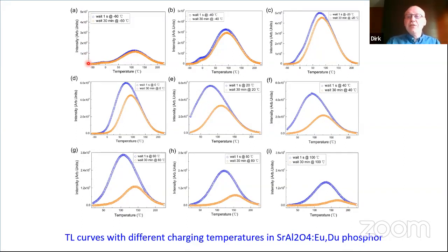It's too cold, and there's not enough thermal energy to liberate these charges from the persistent phosphor. So this also means that we cannot use strontium aluminate with europium and dysprosium at this low temperature. And then we make the same measurements at higher and higher temperature. We can see minus 40 degrees. There's a little bit of light emission when we wait for 30 minutes at minus 40 degrees, because there's a little bit of difference between the two curves, the thermoluminescence measurements without waiting and with waiting. And we can see the higher the temperature, the higher the difference between these two curves.